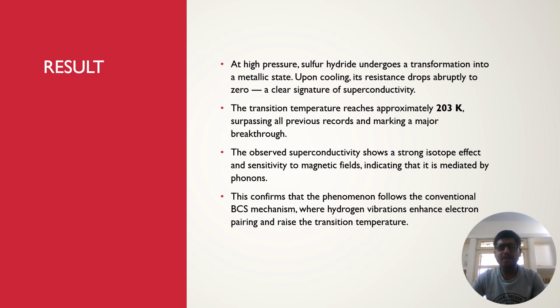Upon cooling, the electrical resistance drops abruptly to zero, which is a clear signature of superconductivity. The transition temperature is around 200 Kelvin, which is significantly higher than most conventional superconductors. A strong isotope effect is observed, meaning that replacing hydrogen with a heavier isotope reduces the transition temperature. This confirms that phonons play a central role in the pairing mechanism.